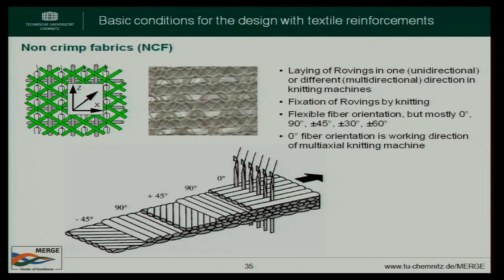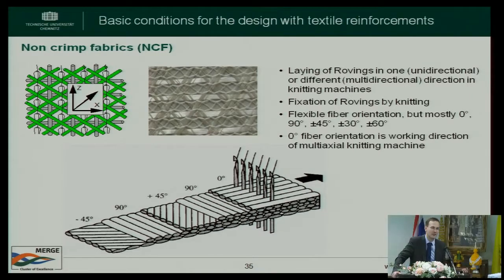You have a stitching process for fixation of your fiber rovings inside of the non-crimp fabric, and you can lay your rovings in different directions. This is more efficient for producing load-adapted fiber reinforced plastic structures, because you can adapt your fiber orientation to how the force flow is inside of the part, instead of weaving, because in weaving you always have in the basic layer 0 degree and 90 degree.